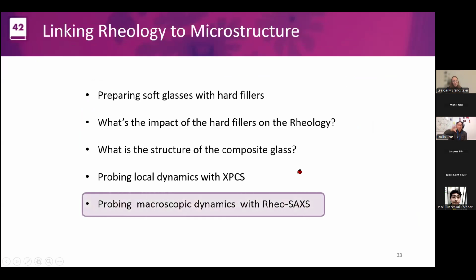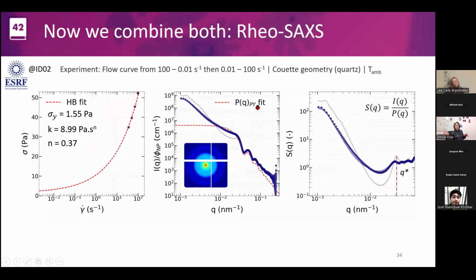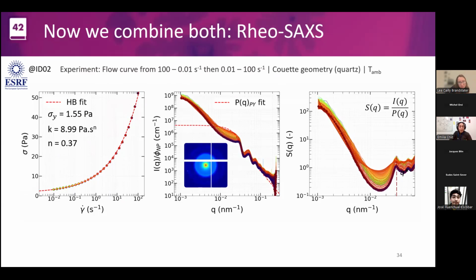Now we can link the whole thing, so rheology and microstructure. And what we do is that we combine the two. So we irradiate the sample with the X-rays at the same time as we do the rheology experiment. So the flow curve in the experiment is a flow curve that goes from high shear rate to low shear rate, and then again up. So it's a down-up experiment, from a low shear rate to higher shear rate in a Couette geometry. And if you see, this part here is the rheology experiment, you're now familiar with this representation of the soft glass. So it's a soft glass that is flowing and has a yield stress. So at very low shear rate, it stops flowing.